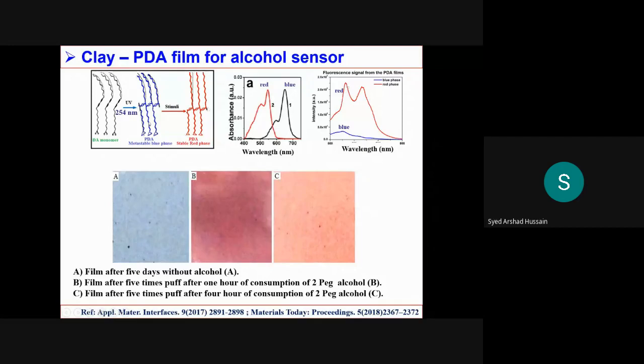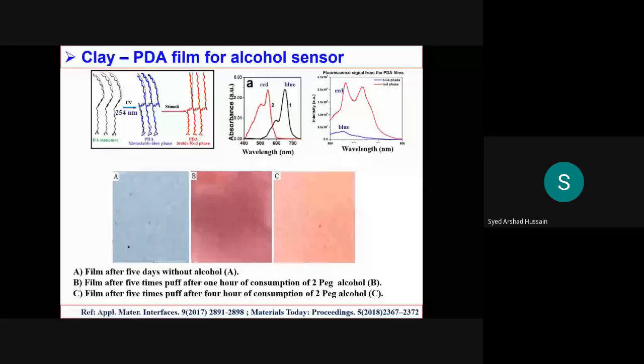So what one can do, the main importance of this PDA is that once you prepare your PDA in the blue phase, and then you expose it to different stimuli, for example heat, or different external perturbation like UV or the presence of other material, and if it changes its phase from blue to red, you will see the change, and it's observable under the naked eye, this blue and red phase. So this material is very suitable for colorimetric applications, naked eye applications. In this example, we use one organic material, and then clay, and then PDA. It's a mixture.